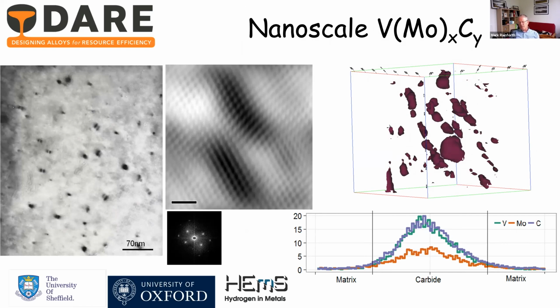And then on the right-hand side, we have the atom probe here, showing lines of precipitates, in this case, vanadium carbides with a tiny bit of molybdenum, which is a crucial addition in there, which refines the structure and gives us this really high number density.